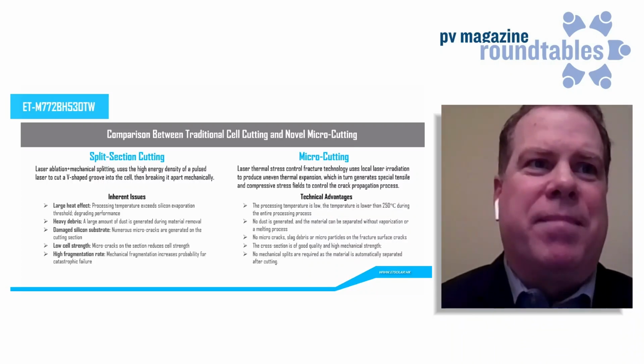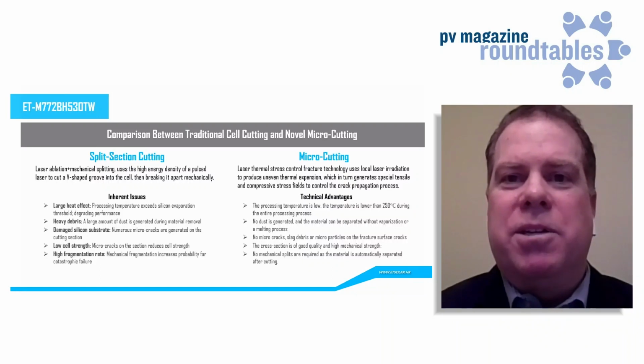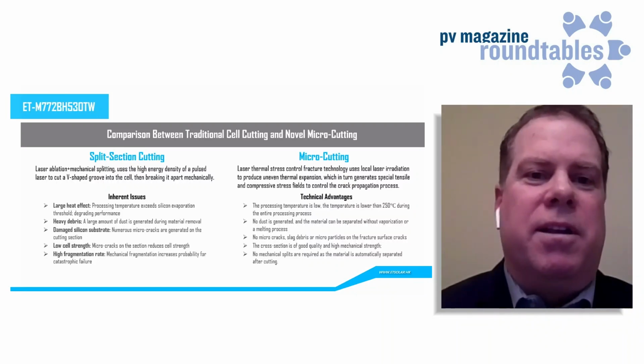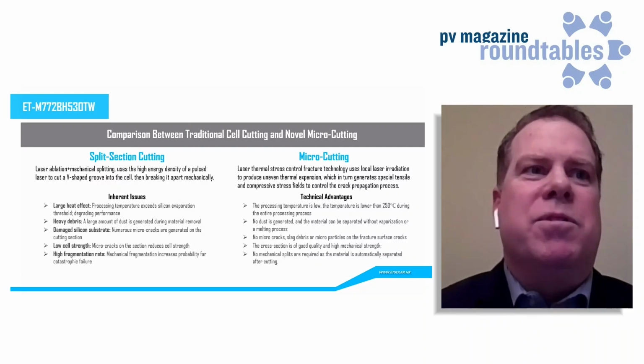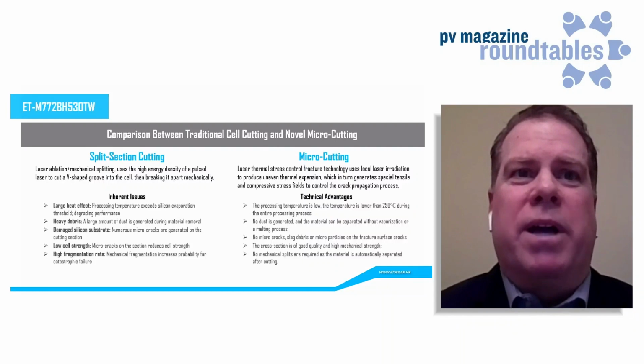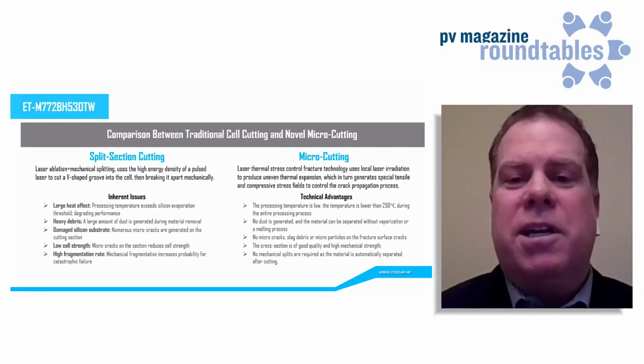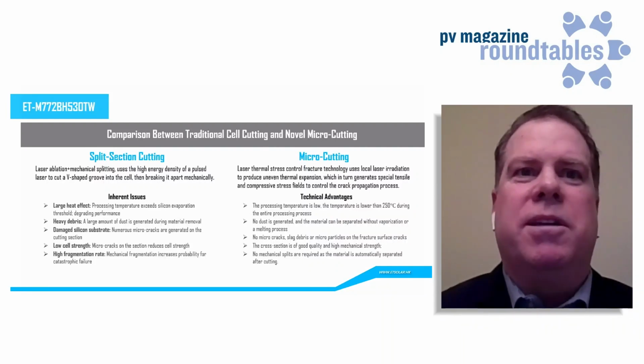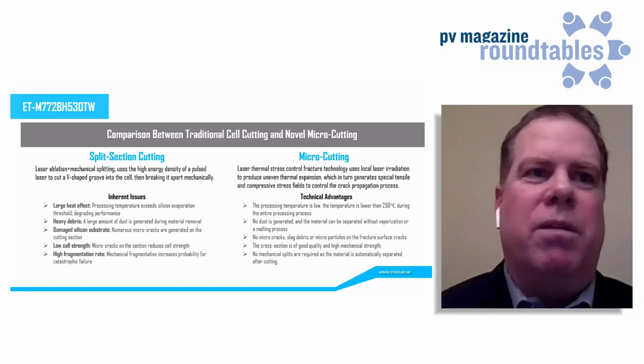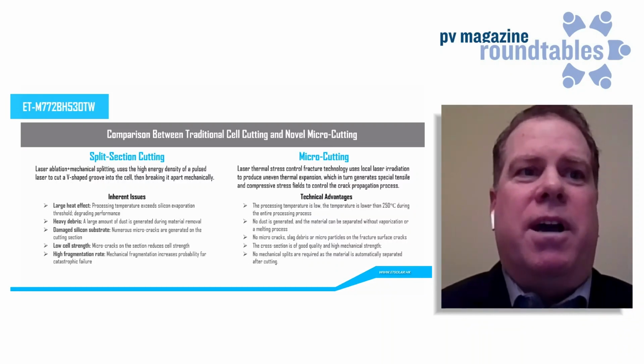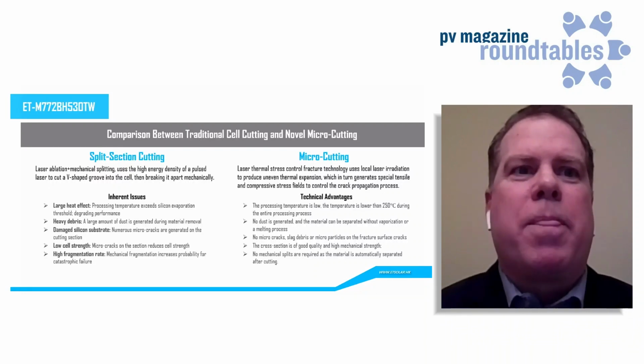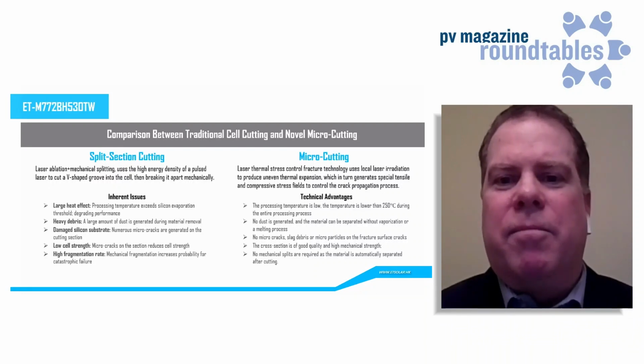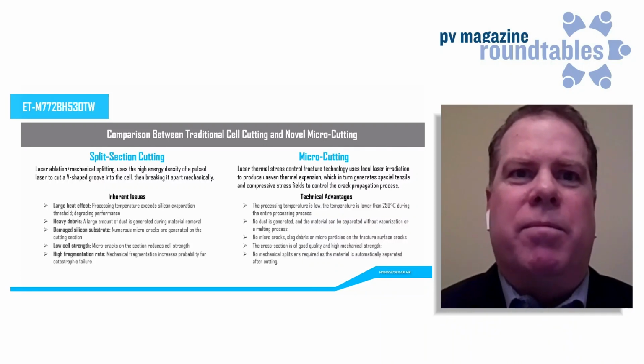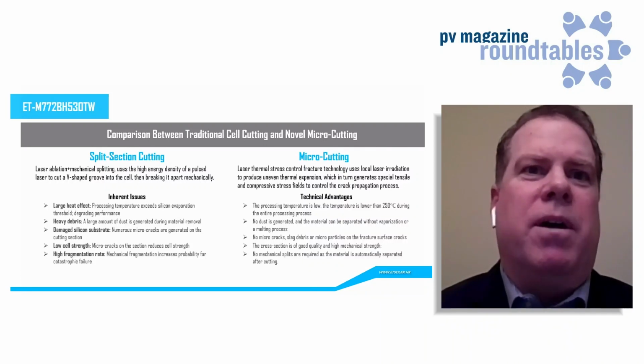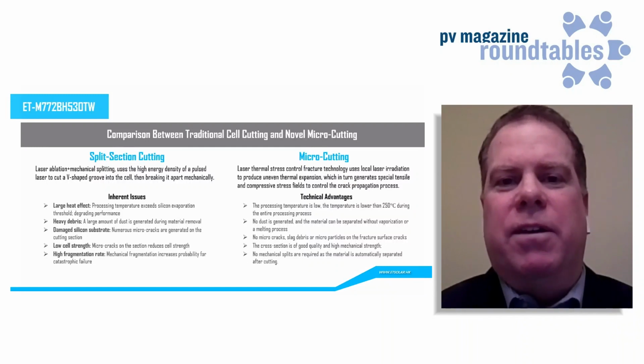There's also some debris that is created from that ablation process. This introduces a dust and potential contaminant throughout the rest of the processes. There's the damaged silicon substrate, so there's numerous microcracks that are generated on the cutting section. These microcracks lead to a reduced cell strength, which can lead to further problems in the module. And there's a higher fragmentation rate. So as these cells are broken apart through a mechanical break, this increases the probability for catastrophic failure.